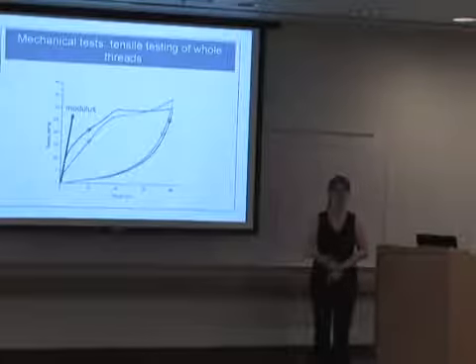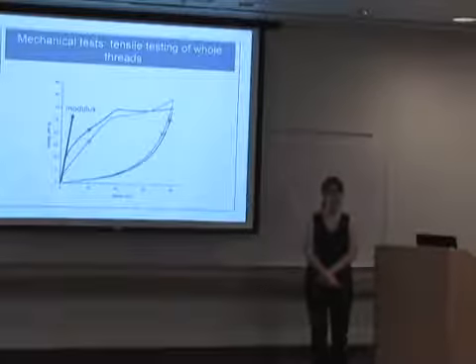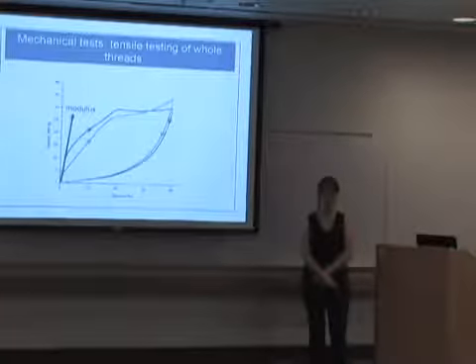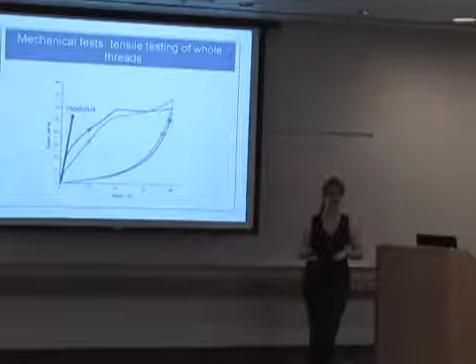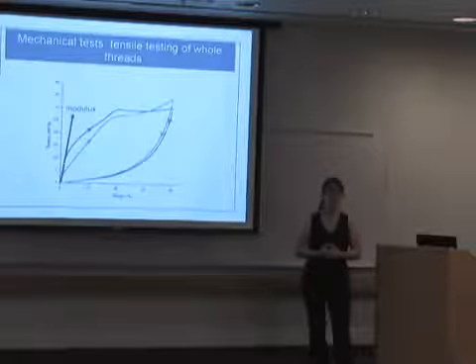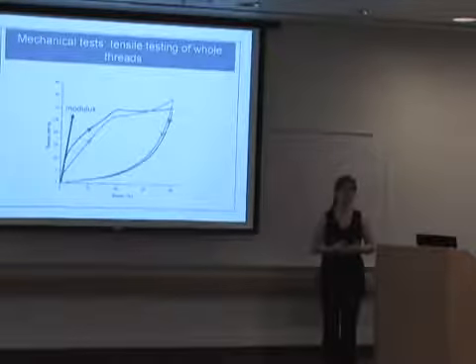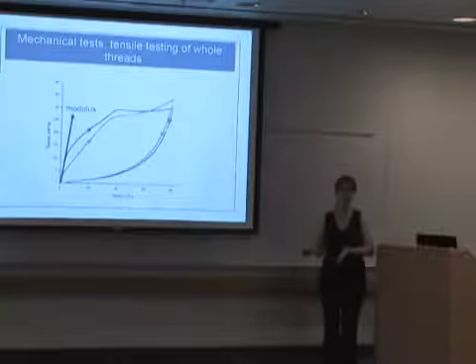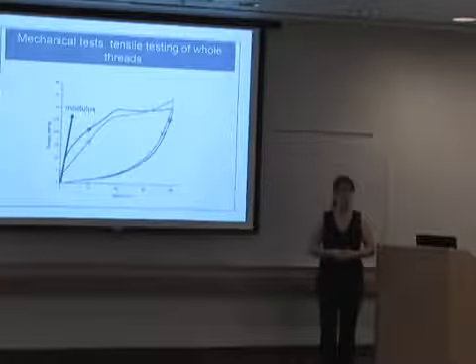Yes. You said you were working in pH 5-ish, right? Yeah, about between 5 and 5.2. Is it safe to assume that the mussels themselves wouldn't be at such a pH? And do you know how you could account for such a difference in the pH? I'm not sure how mussels would react in that pH, but I was not actually soaking the mussels themselves in my iron treatments. I would harvest the threads from the mussels and then soak them in the solutions. I don't think they would like being in a pH that low, but they're pretty hardy organisms, so I don't know how they would react. But they're usually used to being in a pH of around 7 or 8, which is the pH of seawater. The reason I lowered the pH is because at 7 or 8, the iron would not be in the Fe3+ form. So I wouldn't be able to assume it was being absorbed by the threads.